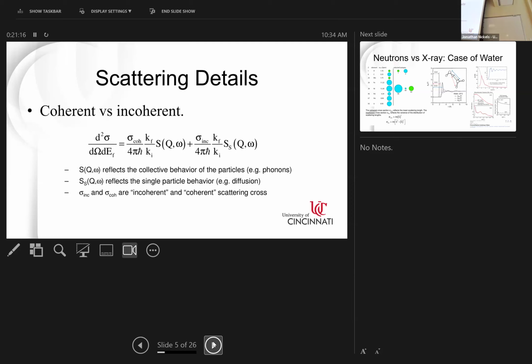So if I see a proton in water and I'm doing a backscattering experiment, the dynamics I'm observing are generally, not entirely, but the majority of what I'm observing are translation and rotation of that water molecule. So it's moving itself, and you're seeing the protons in that water moving as a function of time. And then the wave vector is telling you how far they moved. So you can think of it as an incoherent scattering experiment.